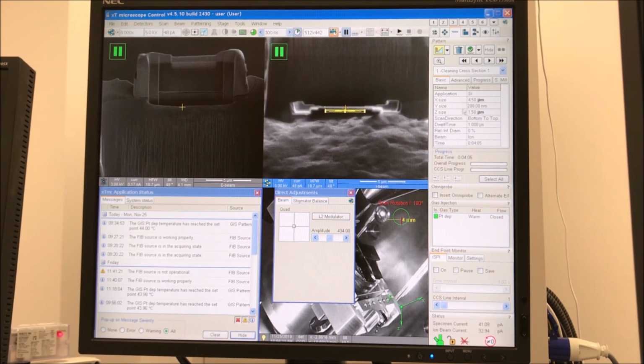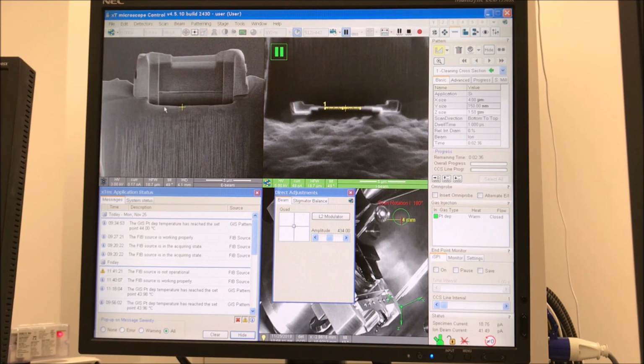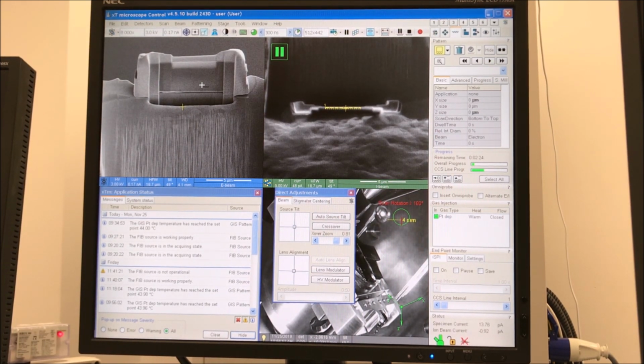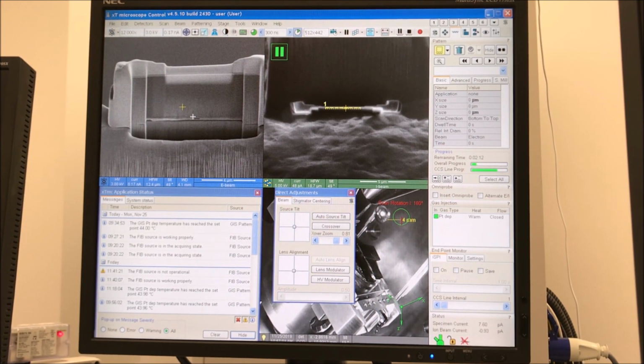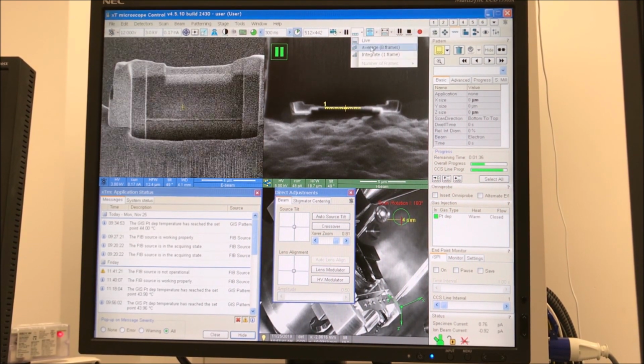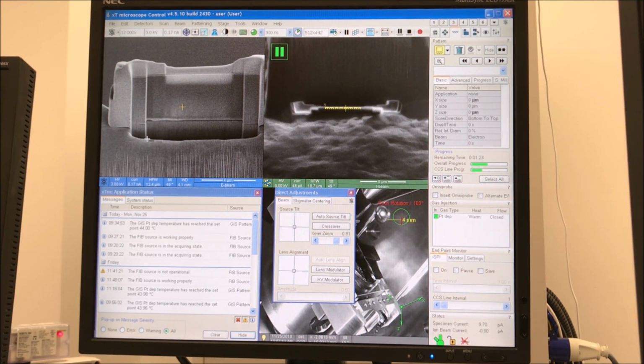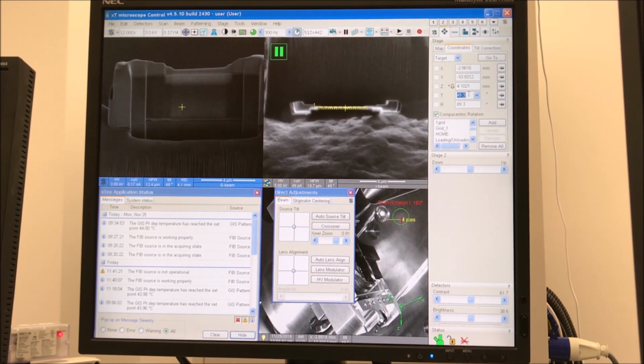And I'm going to wait a little bit here to make sure that the drift has settled down. It should go away pretty quick, but you need to be patient and then go ahead and start the pattern. So now again, we're milling the side that we can't see directly with the E-beam, but we might be able to see now because we're cutting again a staggered pattern into the other side. We might be able to see that window here as the sample gets thin. So my platinum's starting to get thinner, which is good. Although we don't want it to go all the way away yet because we still have more milling steps to do at 2 kilovolts. So we're going to stop this now.